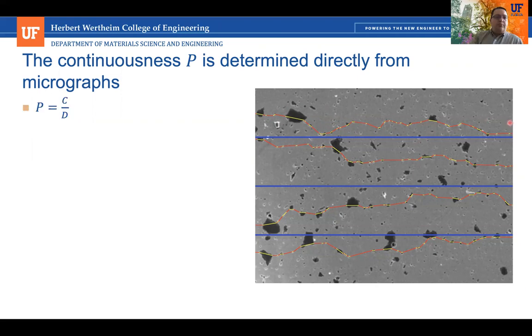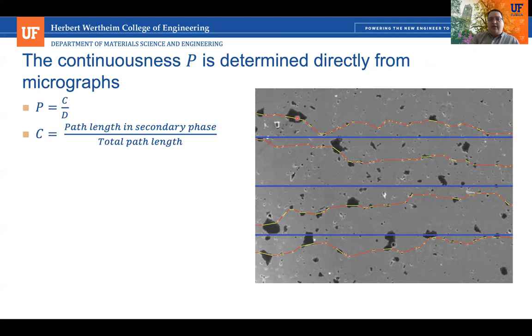And so we end up with this parameter P, which is a function of C, where C is the path length that's in the secondary phase divided by the total path length. So this sort of winding path. And then D penalizes paths that are not straight. So we take the total path length and divide by the actual width in the direction of heat transport, which would be the shortest path that you could follow. And from that, we get this value for P.